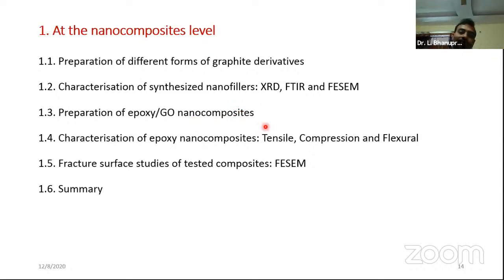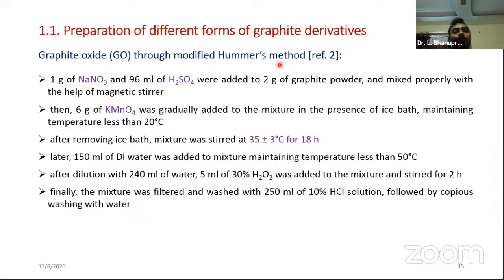Then we adopted a method for generating the nanocomposites. We prepared them and characterized them for tensile, compression, and flexural properties. We studied their fracture surfaces to evaluate the dispersion of the nanofillers in the system, as well as the kind of fracture involved in the specimens. First, oxidation is followed through the modified Hummers' method. Hummers, in 1958, did the oxidation of graphite using three oxidizing agents: sodium nitrate, sulfuric acid, and potassium permanganate, KMnO4.